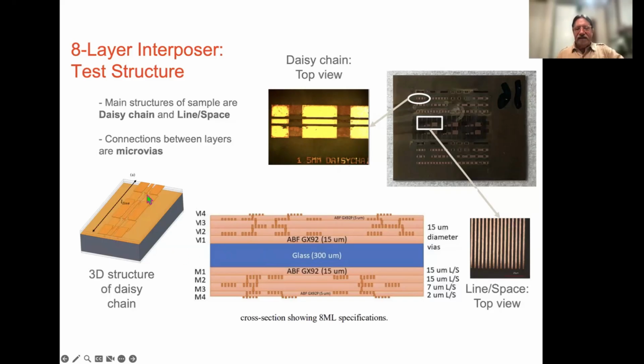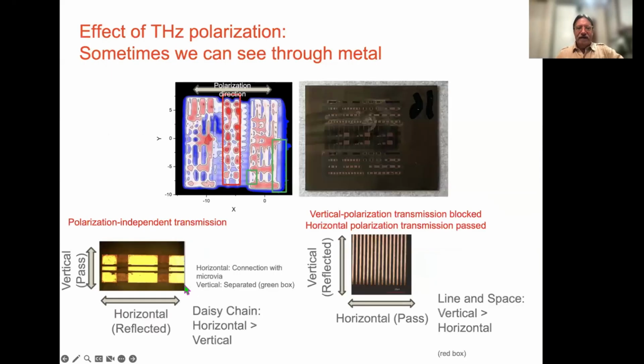The presence of metal is going to present a problem for terahertz, because terahertz is not going to be able to see through patches of metal. But surprisingly, we can see through these lines by using the terahertz polarization. This is just a top view of the test sample showing these different test patterns of line space and daisy chain. Depending upon the terahertz linear polarization, we can see through these lines and see lower lying defects. If the polarization is horizontal, we can see through the lines. If it's vertical, the signal is reflected.